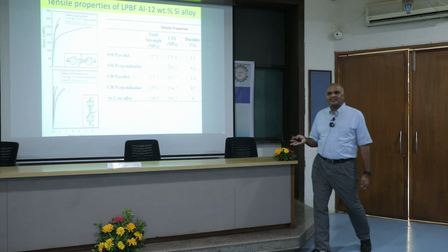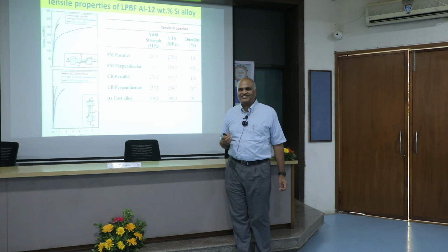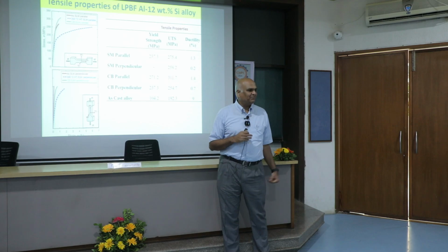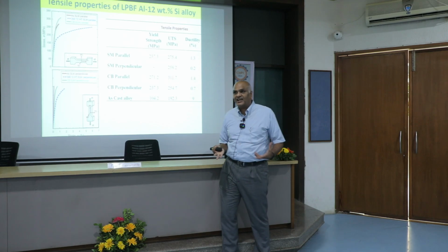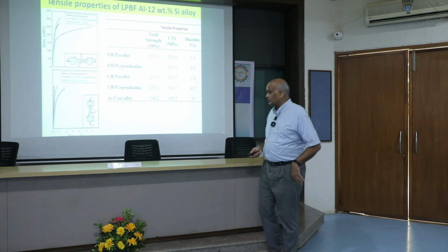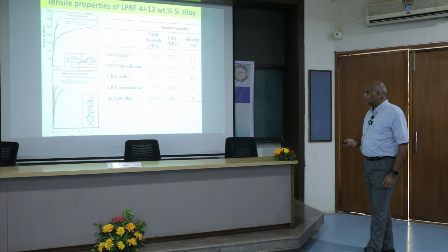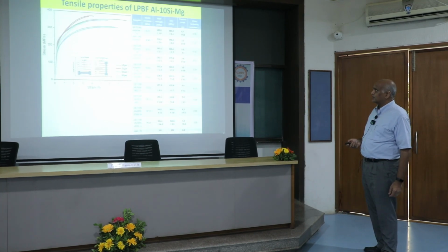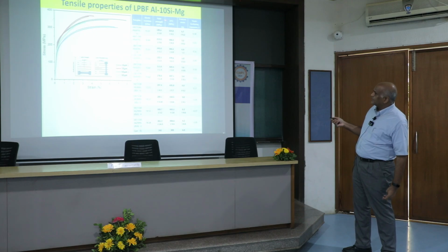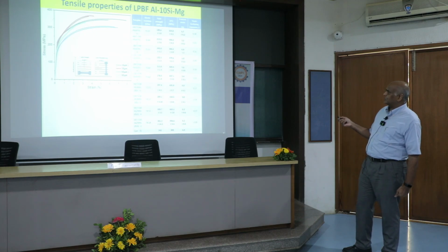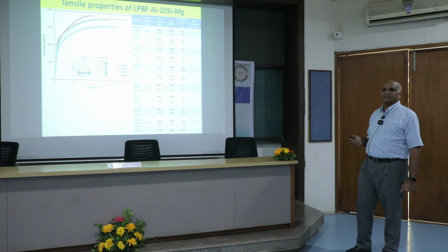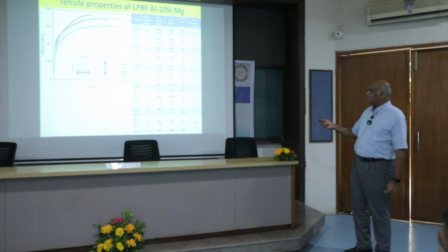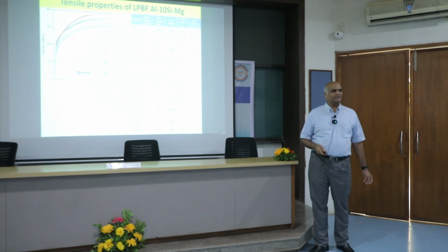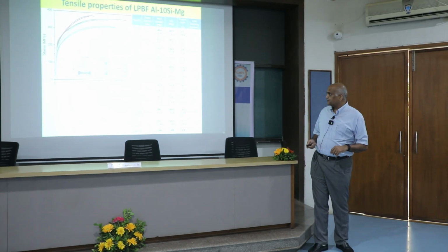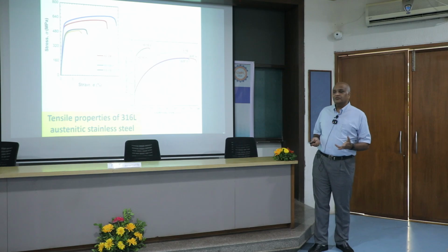So if you take it to a mechanical engineer and say, okay, use this material, they will laugh at you and say, go off, because it's brittle. If you look at it hard, it may fracture, right? So you gain on strength, but there is a very substantial reduction in ductility. Okay, we have another variant of this, with slightly less silicon and magnesium, same story. Here we have some ductility, but compared to the same alloy cast, strength goes up and ductility comes down. Okay, but is it only true for aluminum?